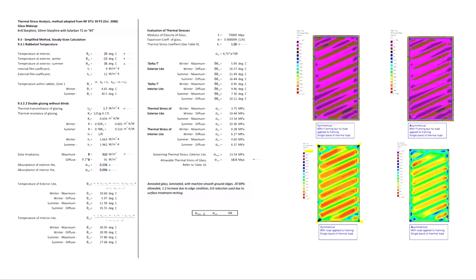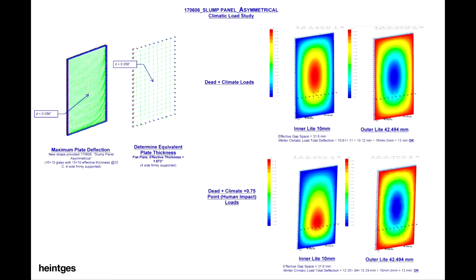We also looked at thermal stress on the glass, with the worst case being a hot differential temperature between the center and edge of the glass in the summer. And then evaluated as well the IGU performance under the climatic loads. We calculated equivalent thickness of monolithic glass that would have the same stiffness as this very stiff laminated outer light.